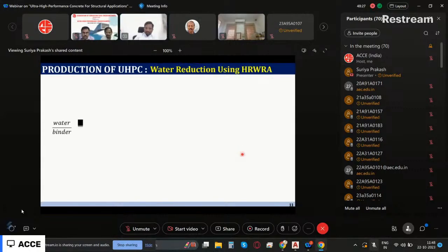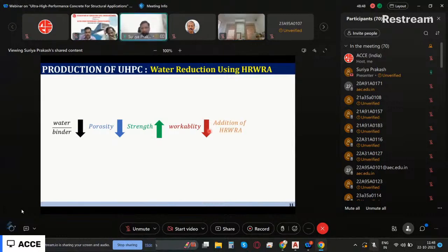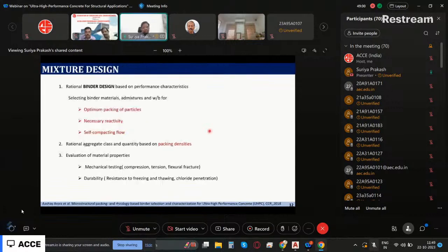Now, we know that when you reduce the water to cement ratio, or water to binder ratio, I can reduce the porosity and strength will go up. That's what we are trying to do in ultra high performance concrete. But what is the cost that we pay? When I reduce the water, workability also reduces. So how do we compensate for that reduced workability? I have to add high range water reducer or superplasticizers. The superplasticizers also should be compatible with the type of cement and type of material that we are using. In that way, we can improve the workability. So this is the idea.